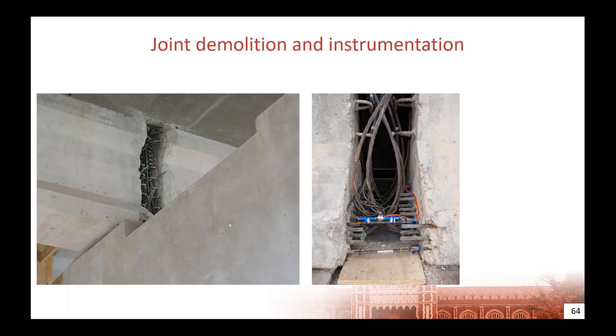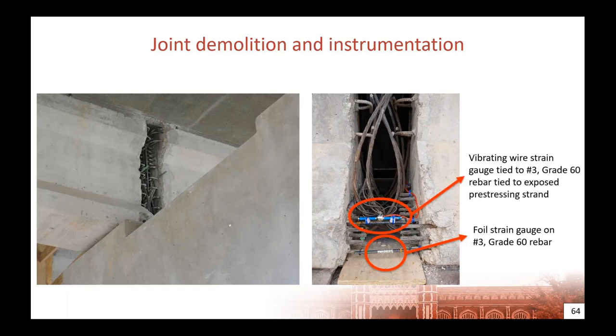So we embedded two different types of strain gauges in two of the joints. The first strain gauge, the bottom one, is a foil strain gauge, a 6 millimeter gauge length strain gauge, typical of steel. And it's attached to a number three piece of rebar, and it was directly tied to the pre-stressing strands that are sticking out of the ends of the girders. And then the other strain gauge is a vibrating wire strain gauge. It's also tied to a number three. And because vibrating wire strain gauges have to have material wrapped around the entire perimeter, they're offset from the piece of bar with some foam blocks. That way, whenever the UHPC is poured, it'll completely envelop the vibrating wire strain gauge.